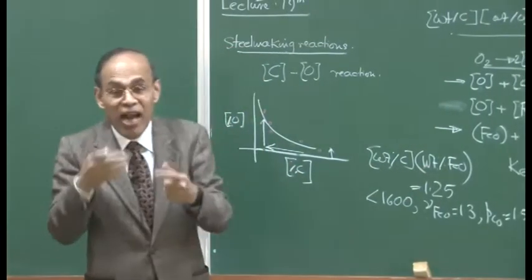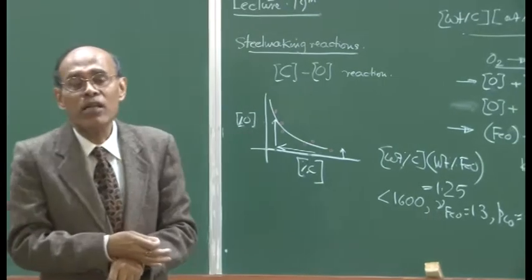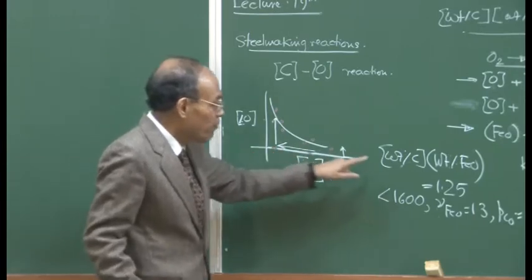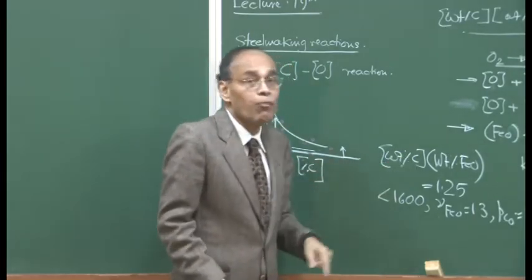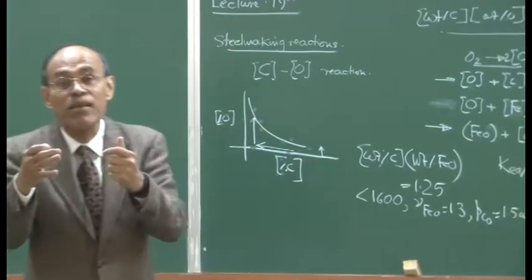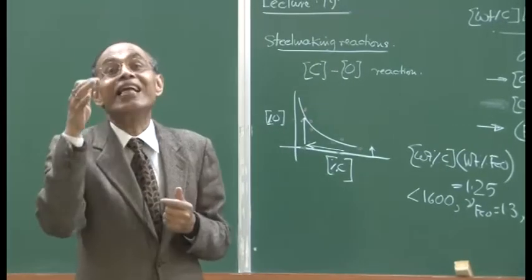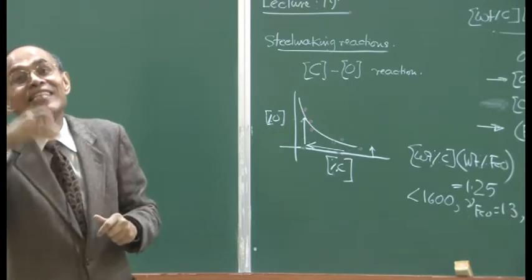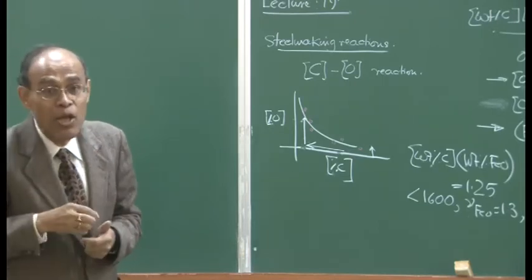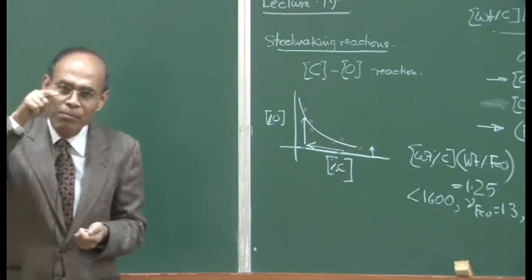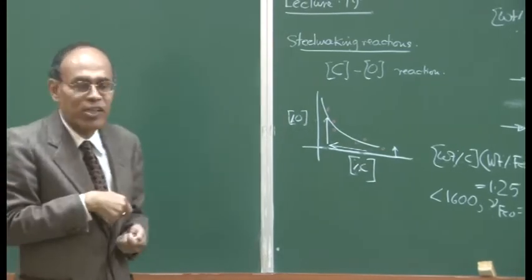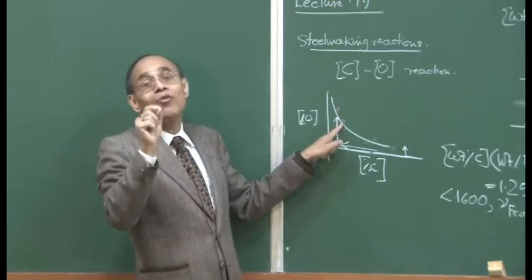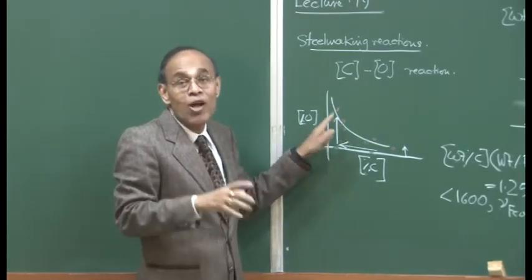And this large scale FeO oxidation will occur particularly when the carbon content is very, very small. At that point, the last period is going to be prone to yield losses. You want to produce steel, but your steel is landing up as FeO in the system. So if you tend to blow a little more than the desired amount of oxygen into the bath, suppose you have reached your carbon content and now you put in a little bit more oxygen, what will be the consequence?